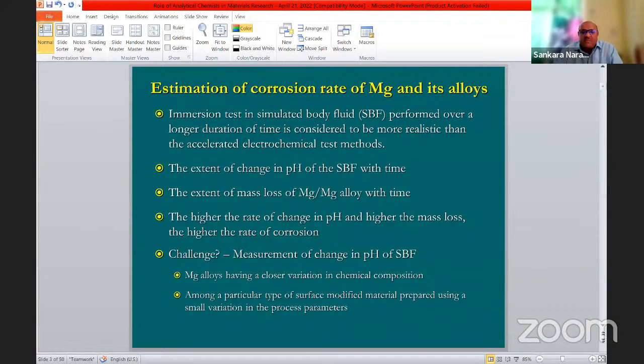The problem is, we can measure the change in pH of the medium using a pH probe or pH electrode. But if you are developing magnesium alloys with a close variation in chemical composition, or slightly modifying the magnesium with a coating prepared under varying process parameters, then there will not be much change in pH among them. For example, if you prepare a coating at 2 or 3 different temperatures and measure the change in pH, there won't be much difference. So which coating is better? You cannot rank them.